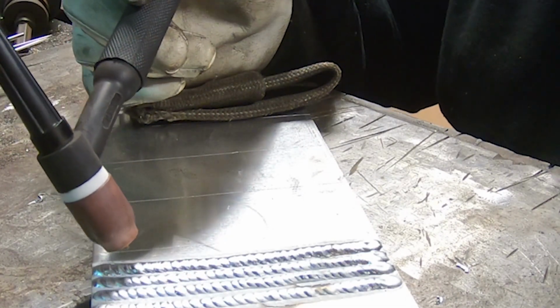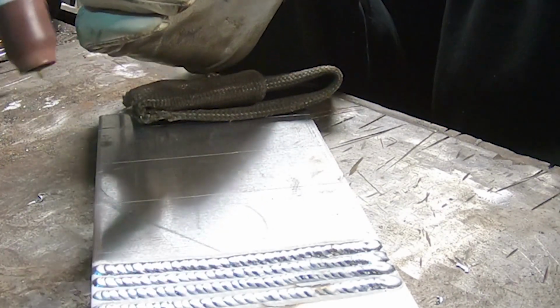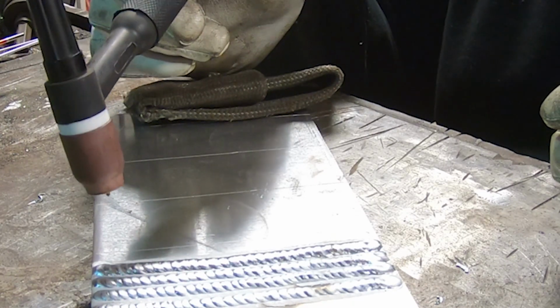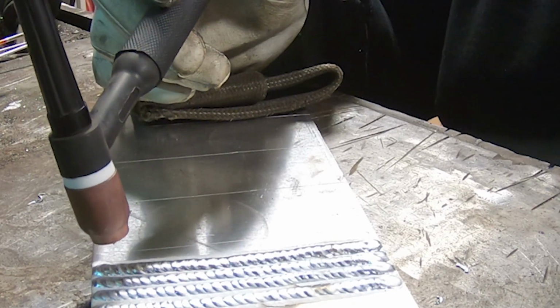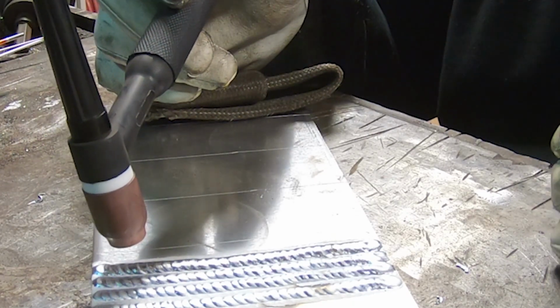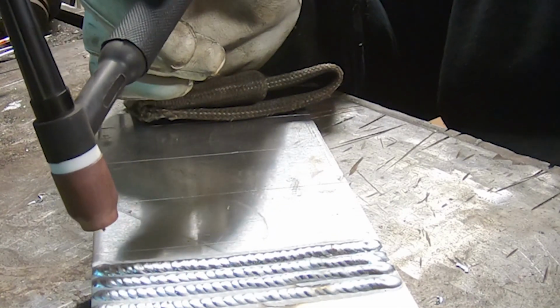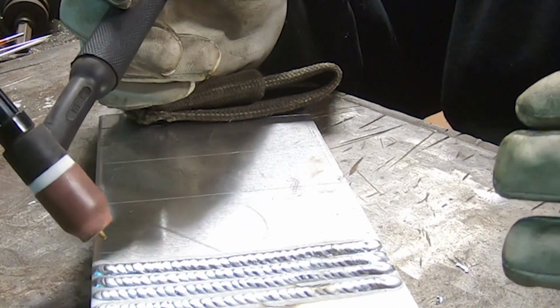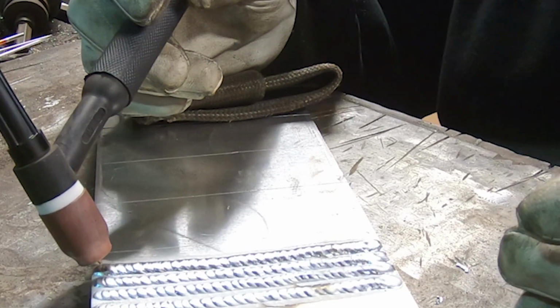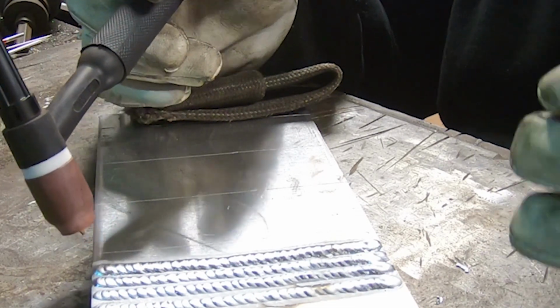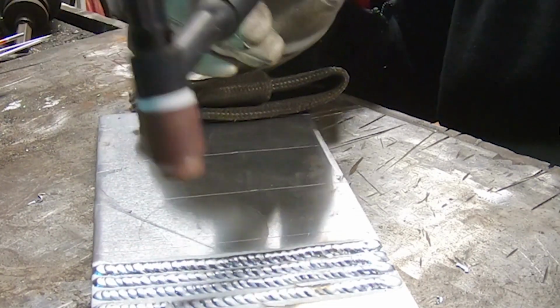What we did on that one is I increased my travel speed a little bit, kept the pedal at full bore, 150 amps, and just made sure that I was adding enough rod to compensate for the heat, which sometimes you can go at it with not enough heat, you won't get enough penetration, and your beads will be a little funky. And that's what happened right here on the second bead.